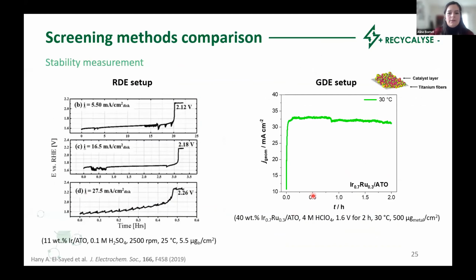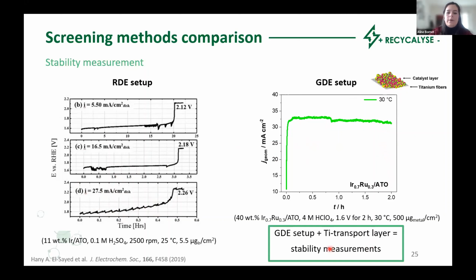And as a final experiment, we compare how suitable our GDE setup is compared to the traditional configuration of the RDE setup for stability measurements. And for that, I reused this publication where the authors saw an activity loss after 30 minutes for a constant current of 27.5 milliamp per square centimeter. And under similar conditions in our GDE setup, our catalyst deposited on the titanium transport layer is stable for 2 hours of testing. So we can conclude here that the GDE setup combined with the use of the titanium transport layer is suitable for stability measurements.